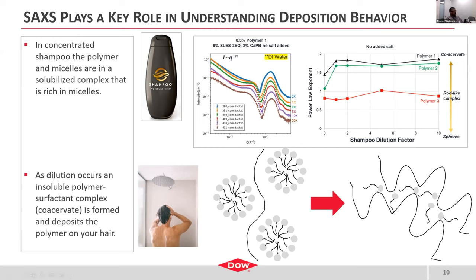When that dilution occurs, another polymer surfactant complex forms called a coacervate, where you get a liquid-liquid phase separation where the polymer becomes the dominant structure and the surfactant begins to be washed away. And this insoluble structure then deposits on your hair.